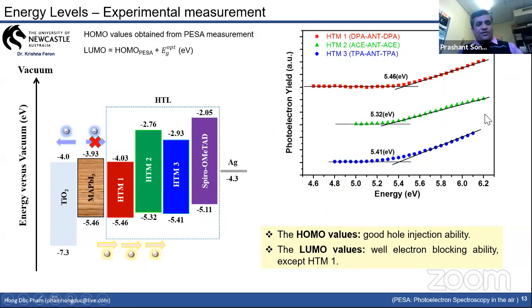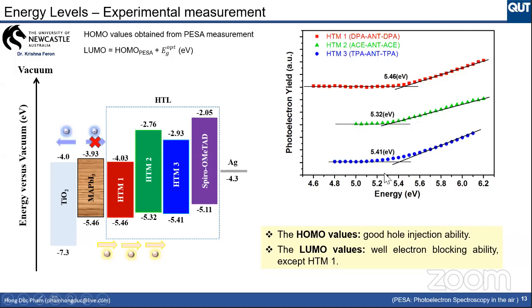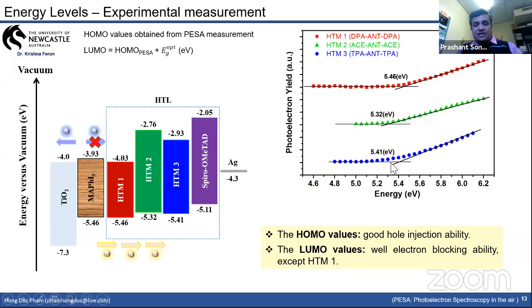Okay, so utilizing these HOMO values, looking at this using the PESA technique, these 3 molecules show HOMO values of 5.4, 5.3, and 5.41. So just with the end-capping group and the core, we can tune their HOMO values. And look at the LUMO values. The LUMO values of this material should not be close to the LUMO of your standard perovskite. Otherwise, they may have the ability to transport electrons as well. So particularly HTM2 and HTM3 are quite far from the LUMO value of perovskite.